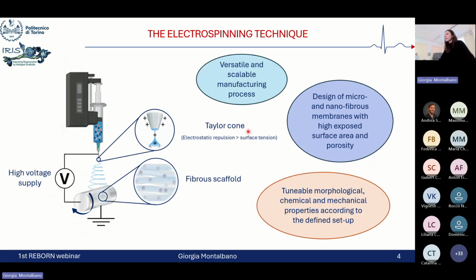The electrospinning technique is a manufacturing process based on the extrusion of a polymeric solution, suspension or melt that is subjected to a high voltage electrical field that stretches the polymer into the formation of a polymeric jet that then solidifies into a nanofiber as it travels toward the grounded collector.